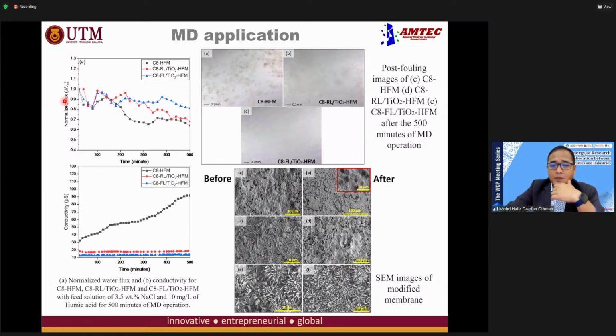Meaning that we can check from the conductivity. If the conductivity of our permeate is still negligible in terms of changes, we can say that the membrane has a very good anti-fouling, anti-hydrophobic property, and therefore it will not have the wetting issue, compared to the membrane without any coating. This has also been proven by the photographic image, and we further proved it by the SEM image, where the before and after for the nanoflower one look the same.